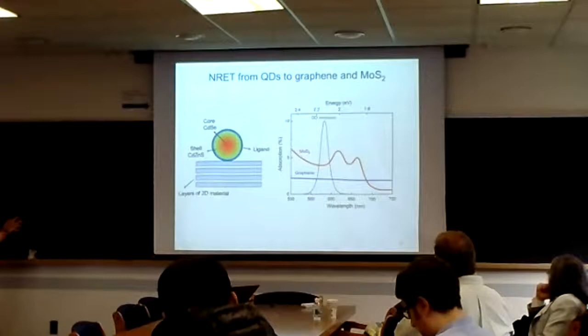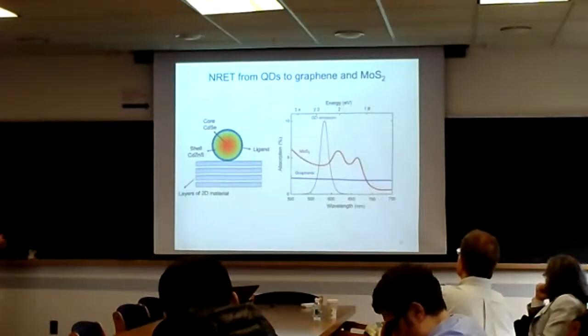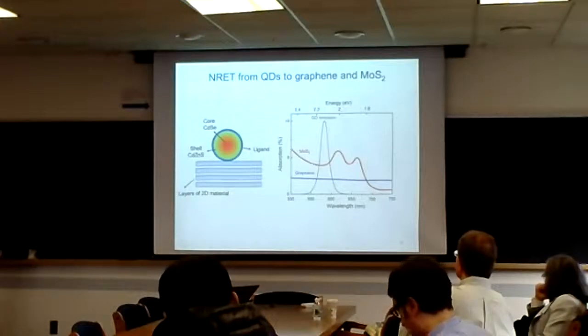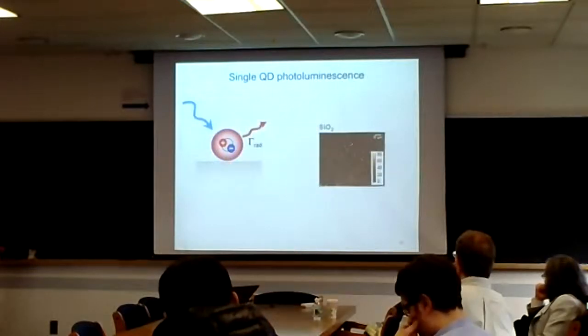Looking at this data, you'd say that MoS2 tends to absorb more and graphene a bit less in the region where this quantum dot emits, and maybe MoS2 would be better at this dipole-dipole interaction. So our first experiment was to look at the wide field excitation maps of these single quantum dots, which have been spread very dilute on an insulating substrate.